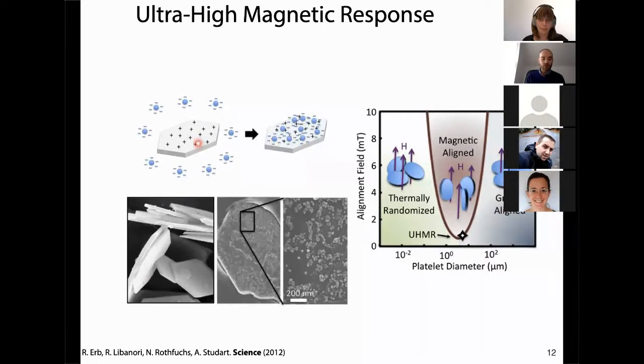And on the surface, we adsorb superparamagnetic iron oxide nanoparticles, so these tiny blue spots. And what the team there realized is that because of the size of these particles, we're at a very sweet spot where you can align them with very little magnetic field. We can control the orientation with very little magnetic field. Just to give you an idea, we're talking about millitesla intensity. So basically, you can control them with a fridge magnet.